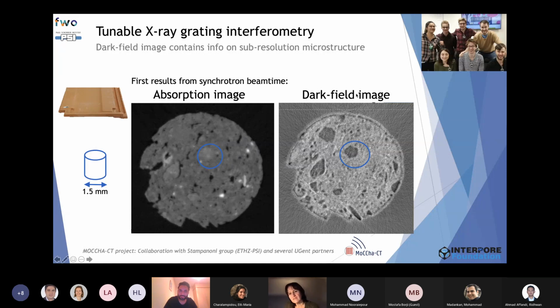So in the dark field image, we see that this area is darker, having almost no signal. This is an indication that there are no pores present, and this is a full grain with no microporosity in this area. By playing with the gratings, we even have the possibility to say there are no grains in the size, in the order, for instance, between 300 and 600 nanometers.